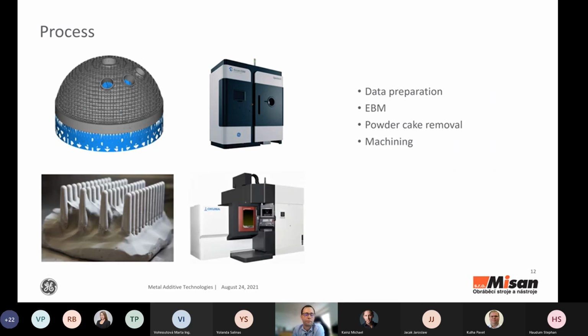A small difference is that it does not need as many supports as laser powder bed technology, but the parts are created in such a powder cake. You can see here on the picture in the left bottom a cake half blasted away. These parts are trapped in such a semi-sintered, semi-glued powder that you have to blast away. The good news is that the blasted powder is again recyclable, and you can use it again in the machine, so you don't lose that.